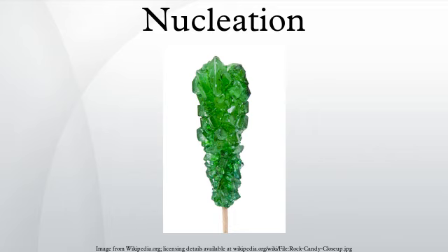Note that this simple theory treats the microscopic nucleus just as if it is a macroscopic droplet. In the schematic to the right the contact angle between the droplet surface and the surface decreases from left to right, and we see that the surface area of the droplet decreases as the contact angle decreases. This geometrical effect reduces the barrier and hence results in faster nucleation on surfaces with smaller contact angles.